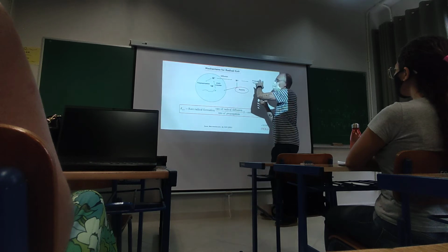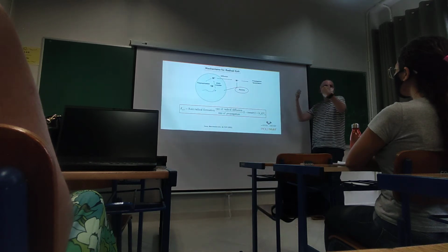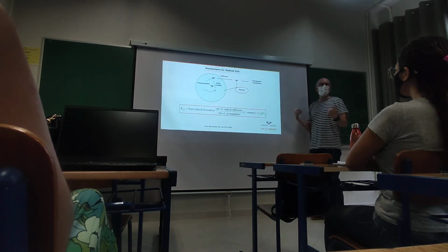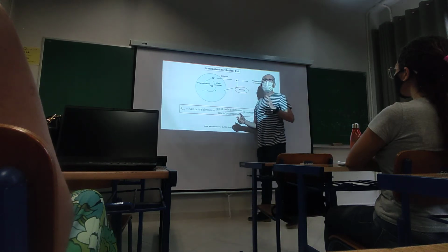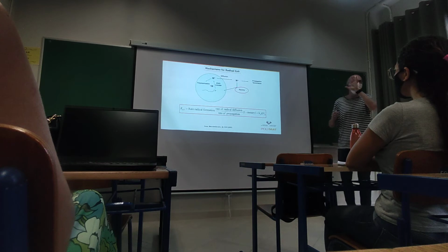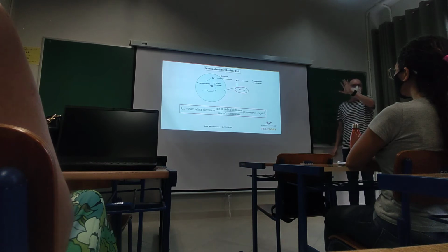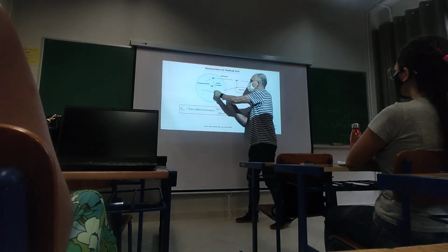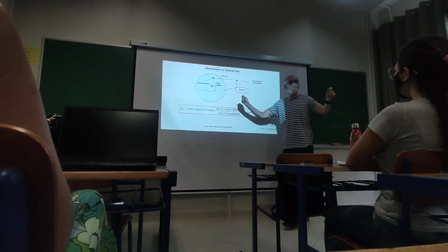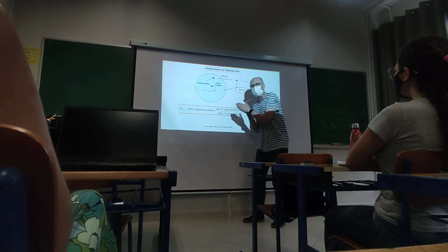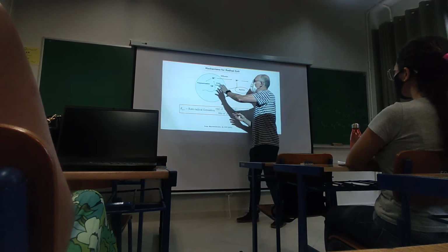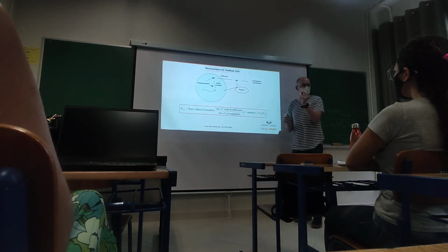It won't be like in the aqueous phase, where they are still very short, because the polymerization rate is too slow in the aqueous phase, because the concentrations are very low. Here, monomer concentration is very high, because we have only monomer, basically, monomer and polymer. So monomer concentration is high, so here the chains will grow fast. So the only radicals that are assumed to be able to exit are monomeric radicals, short radicals.